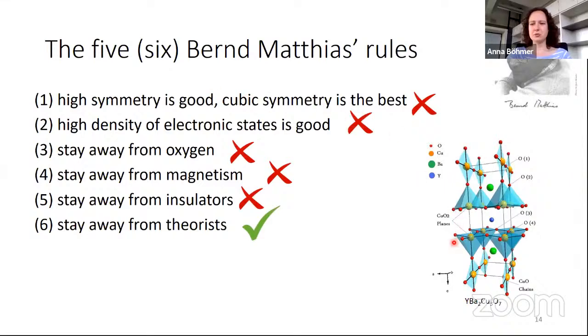They are very much two-dimensional, basically the opposite of cubic. There is a very low electronic density of states. They are oxides. Here's an example. They are magnets, at least in their undoped state, but there's magnetism there. They are almost insulators. The only rule that's still valid is, well, the theorists couldn't predict that. So that one still works.